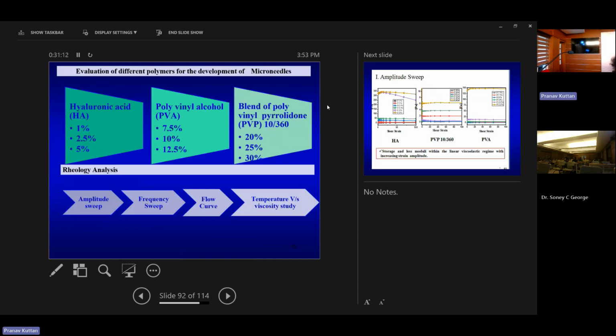So here we have chosen hyaluronic acid, then polyvinyl alcohol, and a blend of polyvinylpyrrolidone, like 10/360, because that combination gave a very good microneedle. We initially tried different concentrations. The first thing we did was rheology analysis. As I said earlier, for this polymer, we want to know how easily it will fill into that mold. The rheological parameters of the polymer, like viscoelastic properties, are very important. And the drying condition, the curing temperature, etc., we wanted to know. So first we did the rheology analysis.